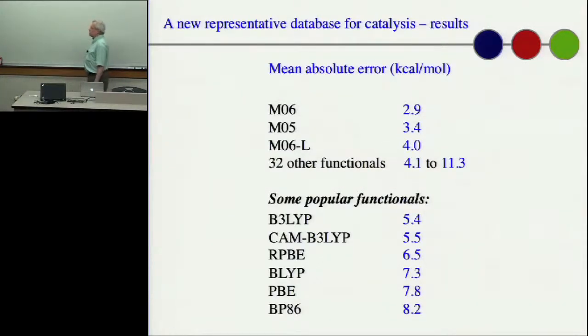So we actually tested 35 different functionals, and these were selected from our previous tests of over 60 functionals as the ones that were most likely to do well. And we found that these 3 functionals developed in Minnesota were the very best of the 35, with mean errors on that database of 3 to 4 kcal. And the other functionals had errors up to 11 kcal.